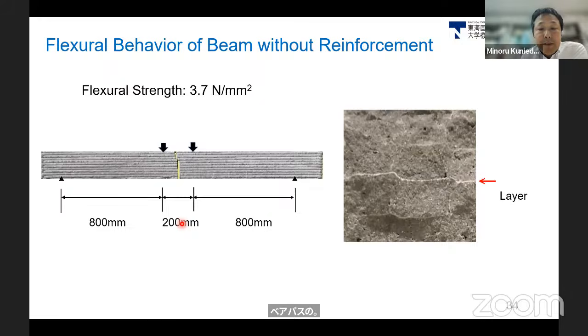So this is the result of the flexure strength obtained from the beams without reinforcement. We observed flexure cracks, single cracks, within the moment constant span, and the flexure strength was 3.7 Newton per square millimeter. And this is a cross-sectional photo, and we can see a white line, right? And this is the sprayed sodium silicate layer, but up to now the effect of this layer is not significant for the mechanical response of the beams.